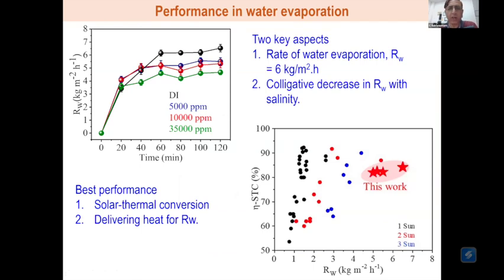And so we went on, and again, pure water at lab scale is interesting, but when you talk about direct applications, salinity or dissolved salts in water is one of the most important and difficult to remove contaminants of water. And when we evaporate water, at least what we saw is, with 90% efficiency in the solar thermal conversion, our rate of water evaporation is about 6 to 6.5 liters per meter square per hour. When you benchmark it with a conventional solar still, it's just doing 1 liter per meter square per hour. So we are already doing about 5 to 6 times higher than a conventional market-ready solar still.